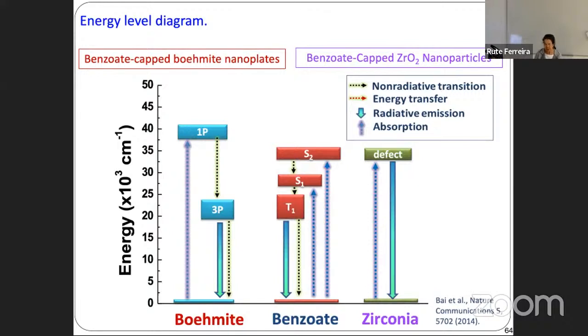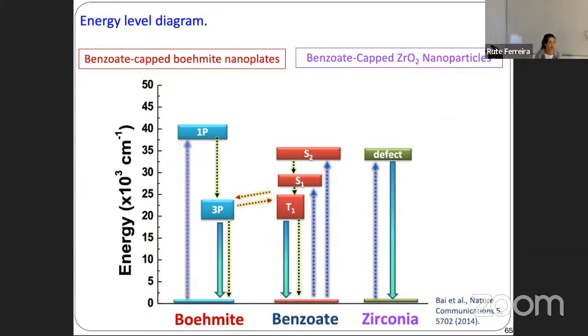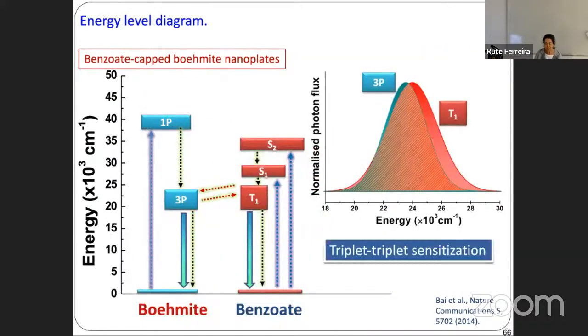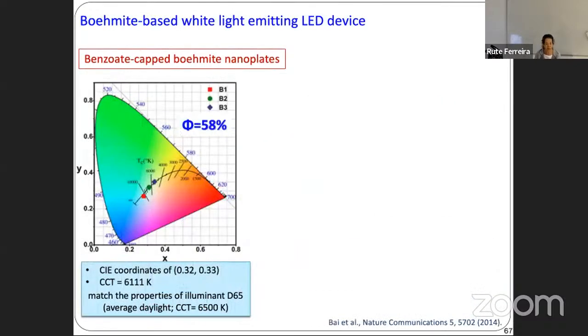And you can clearly see here that there is a resonance, an energy resonance between the triplet state of boehmite and the triplet state of the benzoate. And in fact, this is the so-called triplet sensitization that in this particular case yields a very large quantum yield. So of course, having those two nanoparticles with such a distinct quantum yield, we selected the benzoate capped boehmite nanoparticles to produce a prototype. So B1, B2, and B3 are three prototypes that we developed just changing the calcination time of the nanoparticles. You can see that